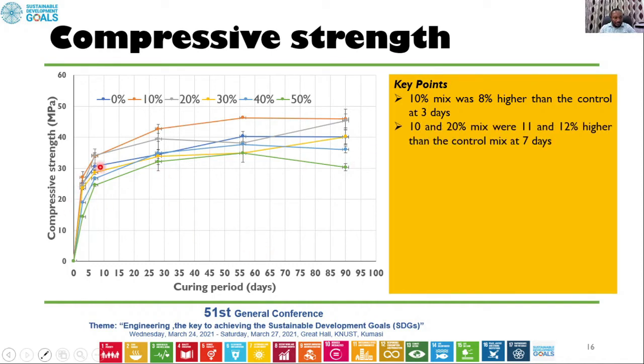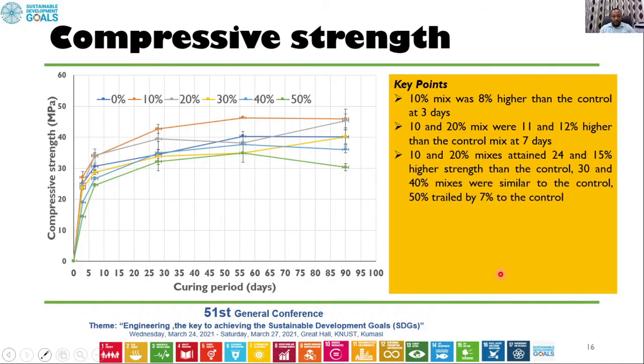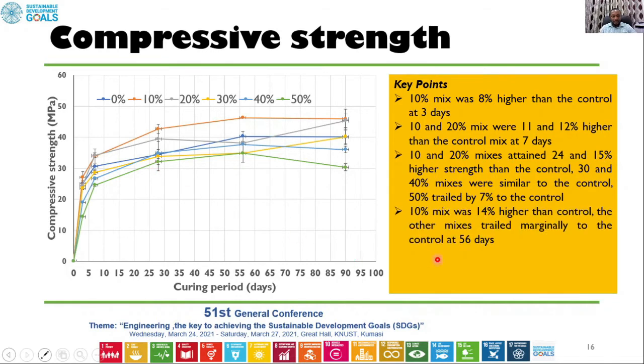And then at 7 days, we have only 10 and 20% exceeding the control. The rest were lower than the control. At 28 days, we have 10 and 20% exceeding the control. But then you see that 30% and 40% were almost similar to the control concrete, whereas the 50% was lower than the control mix.